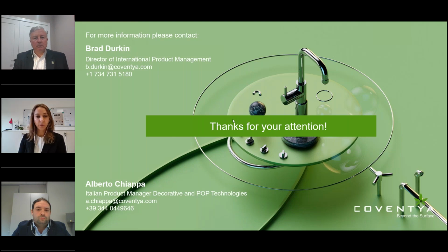Another question arrived. Is carbon filtration mandatory for Tristar 330 AF? It is not mandatory, but it's possible to do it if some organic pollution goes inside the bath, possibly dragged in before the process. Still about pollution, can Chrome 6 pollution be a problem for the Tristar 330 AF? Yes, it's a big problem for the Tristar 330 AF. In fact, when installing the Chrome-free process, it is important that the tank and all the system are completely neutralized to Chrome 6. Okay.